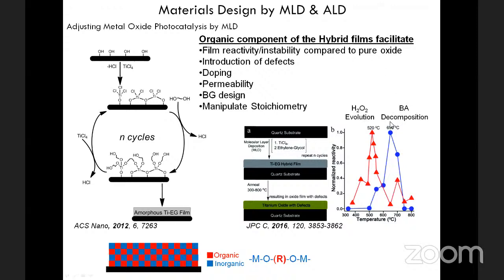And here what you can see is a model test reaction for photodecomposition of benzoic acid, where there is a peak in the activity when the films are calcined at 650 degrees Celsius. All experiments were performed at room temperature, and the temperature specified here is only the anneal temperature applied before using the films. So you can see it has very interesting behaviors. And we started a very long journey to study what are the mechanisms behind these activities.